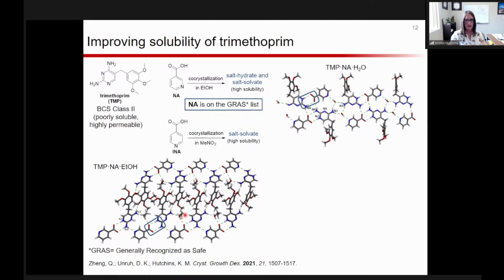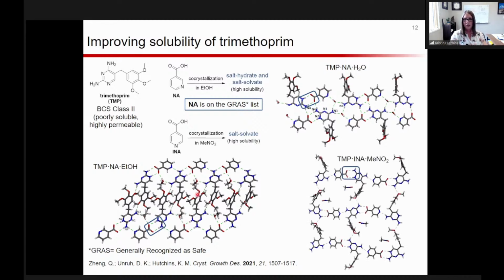So the OH of the ethanol is hydrogen bonding adjacent to the carboxylic acid group. And so that's sort of where it is at. And then third, we have the isonicotinic acid with the nitromethane solvate. Again, same 2-point hydrogen bond we've seen before, the pyridine hydrogen bonding with the trimethoprim NH group, which is similar to this one over here on the left. And these sort of make these square-like assemblies. And then we have nitromethane sitting in the cavity of this one.